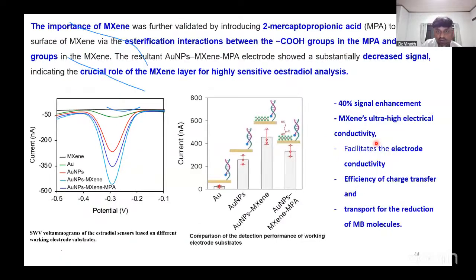The importance of MXene was further validated by the incorporation of 2-mercaptopropionic acid (MPA) to block the surface of MXenes. Here we can identify that without MXene, the electrode shows less than 40% signal enhancement. Here the MXene produces 40% signal enhancement, which is due to the ultra high electrical conductivity and also charge transportation.